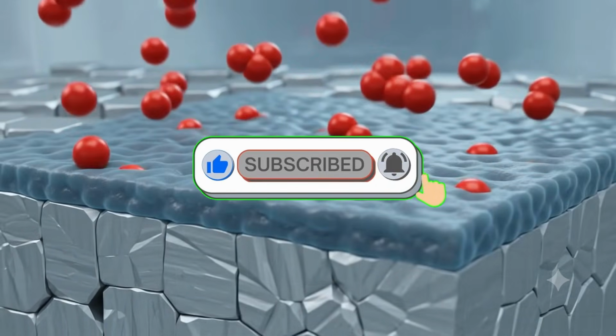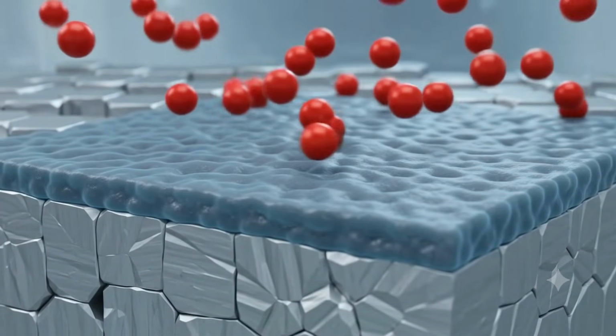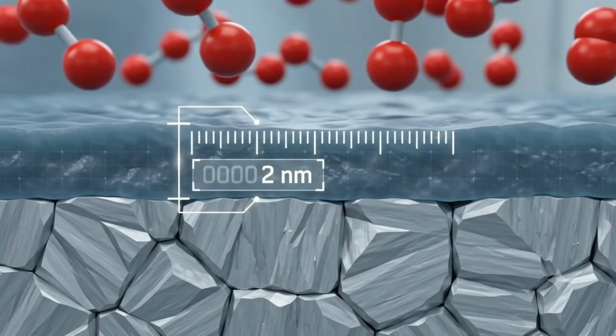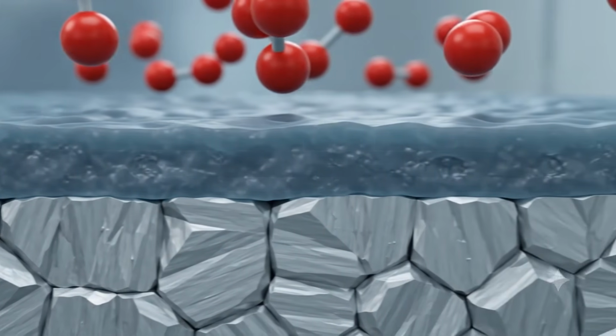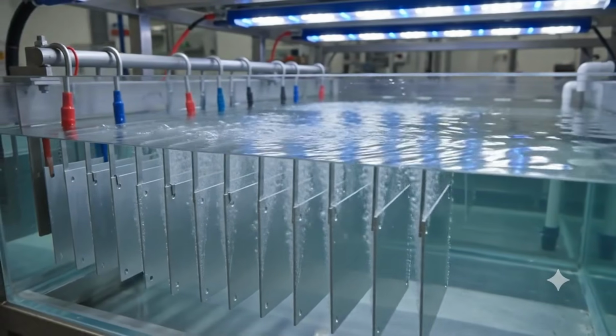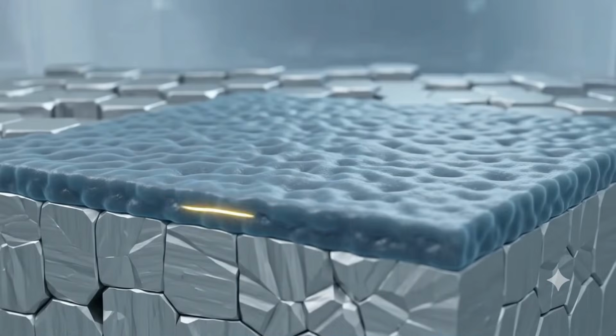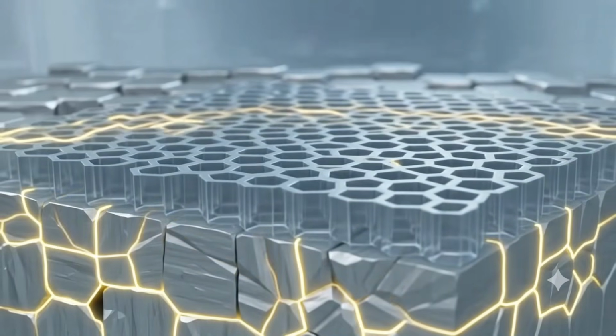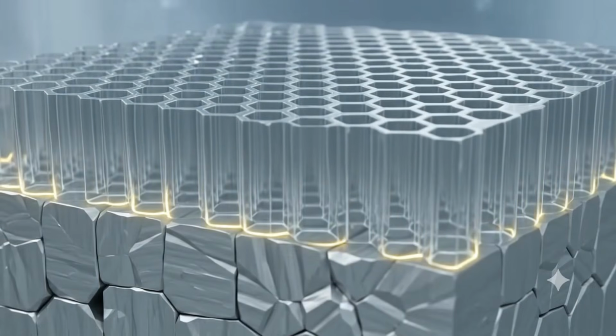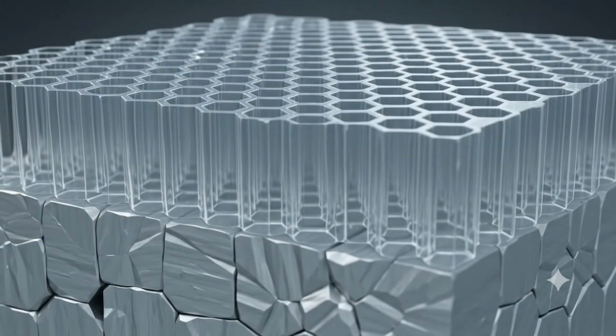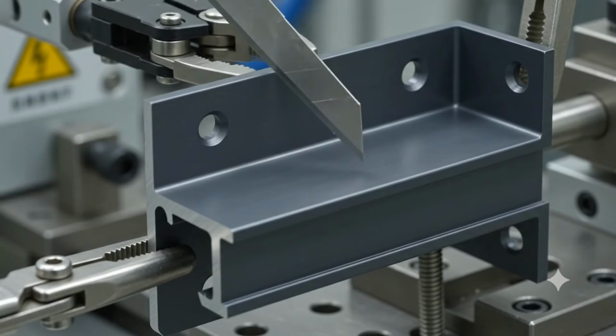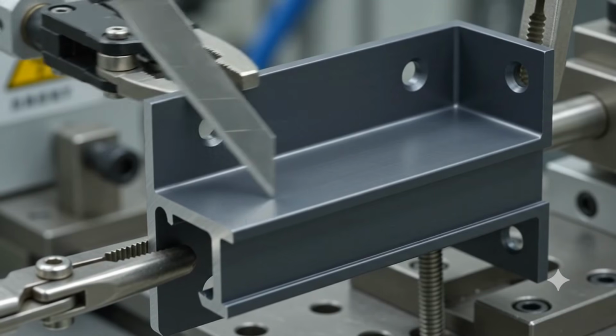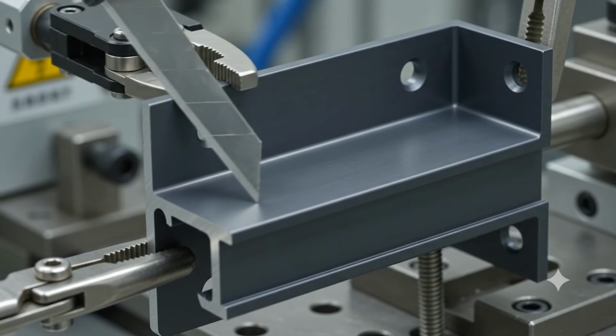Aluminium naturally reacts with oxygen in the air, forming a very thin oxide layer. This invisible layer protects the metal from corrosion, but it's only a few nanometers thick. Anodizing uses electricity and chemistry to grow the natural oxide layer thousands of times thicker. The new layer becomes extremely hard, transparent, and permanently bonded to the aluminium. Unlike paint, it can't peel or flake off because it actually becomes part of the metal.